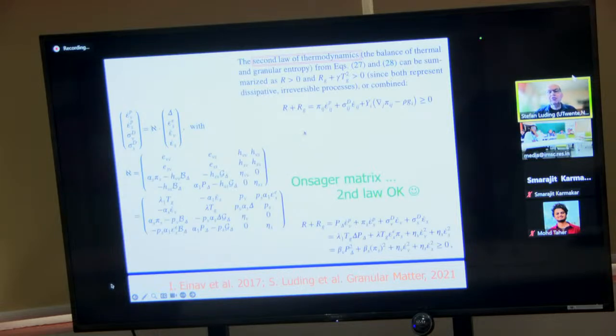Now, if you have a continuum theory, you want to see whether it's thermodynamically consistent, so you calculate the energy and the entropy production terms due to granular and classical temperature. We skip the classical temperature because it's orders of magnitude smaller than the granular. So we focus on granular only. You can work with the Onsager matrix. We analyze all the terms which we have in the theory.